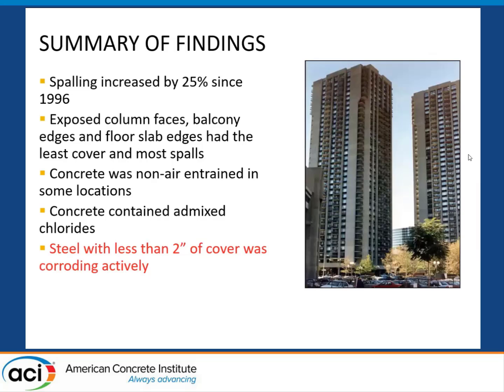But a summary of the findings with all of that investigation was that an investigation had been done in 1996. The owner elected not to do anything. In 2001, they did another inspection, and they saw that the spalling increased by 25%. The exposed column faces, balcony edges, and floor slabs had the least amount of cover and, not surprisingly, the most amount of spalling. There were admixtures in the concrete, which was part of the source of the chlorides that were in the concrete.